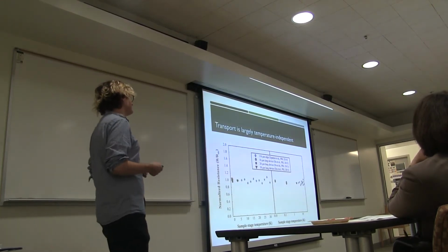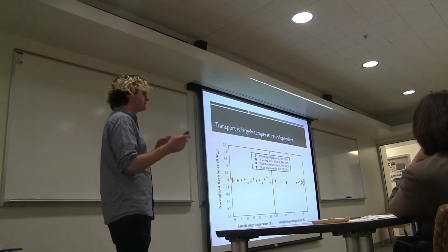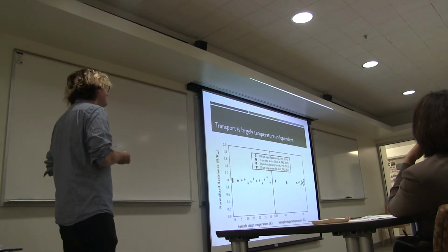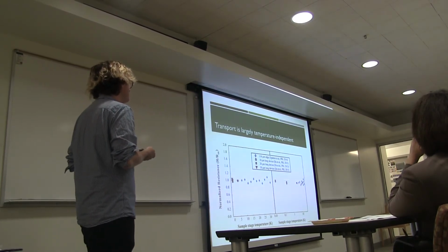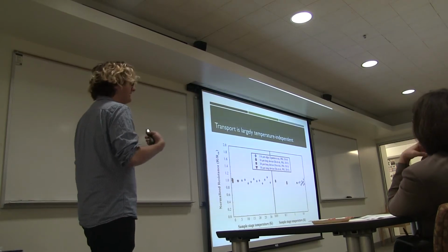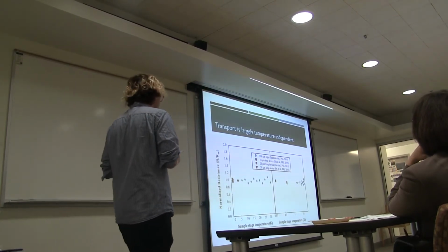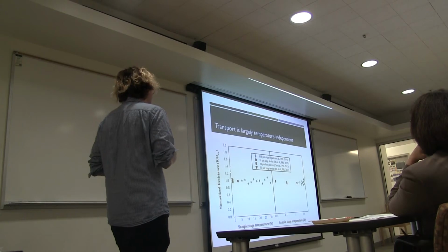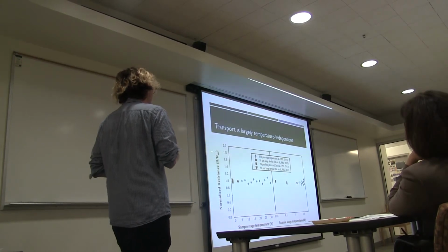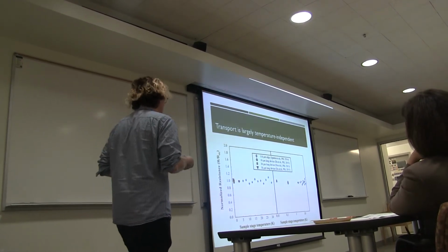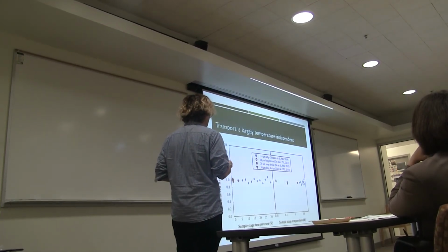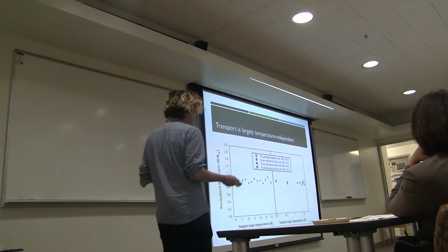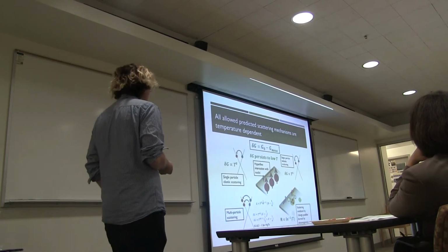And we could also compare this to what's seen in transport at lower temperatures where the bulk is always insulating. And what we find is that over all of the measured temperature range, the resistance doesn't seem to have any temperature dependence to it. So here what I'm plotting is the resistance of each measurement normalized to the 4 Kelvin measurement. And just to show that, in transport at low temperatures, there's nothing really going on, and in our measurements, there's also nothing going on.